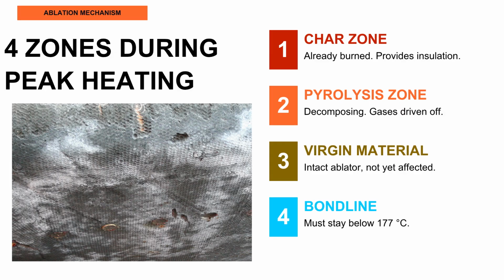The pyrolysis gases are critical. They bleed outward through the char and cool the surface by transpiration, essentially sweating heat away. This is called blockage effect. Remove any one of these layers, and the system fails.